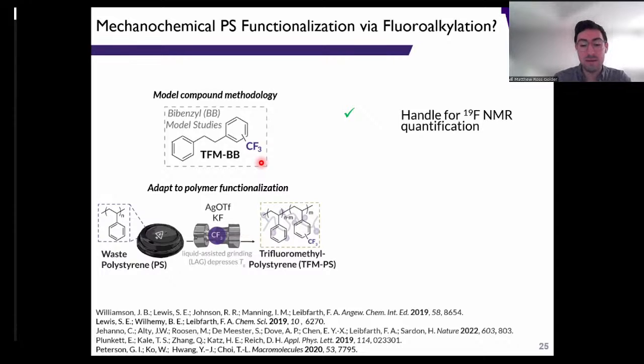So the goal here is to use 19F NMR spectroscopy, which is an extremely sensitive NMR nucleus, coupled with GPC to really assess how these two processes can compete, specifically in the context of post-consumer waste, right? Can we identify conditions that allow us to perform some high barrier post-polymerization modification process without a significant amount of concomitant chain scission? In addition, there are some applications to trifluoromethylated polystyrene, both in the coatings industry and the organic electronics industry. But in this case, we're, again, really interested in just the trifluoromethyl group as a nice functional handle for analytical purposes.